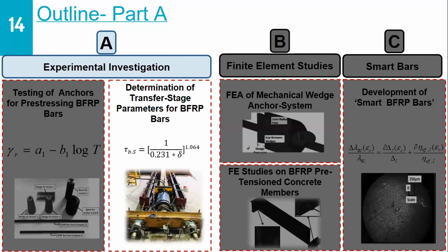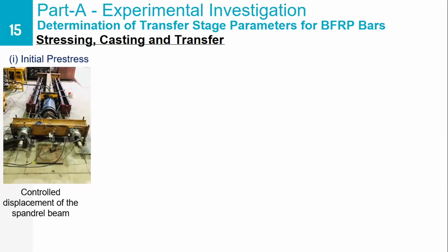So with that, now we come to the second part of the experimental work, which is on the determination of the transfer stage parameters using the setup that has been developed at IIT Bombay. So this is the picture of the setup in which the BFRP bars are pre-stressed by applying some load on this beam. So it's a setup that is a self-balancing frame that has been fabricated, and it has two formworks in which the concrete beams can be cast, and these BFRP bars pass through this concrete beam formwork, and they are initially pre-stressed by applying some load on these beams to which these bars are anchored.